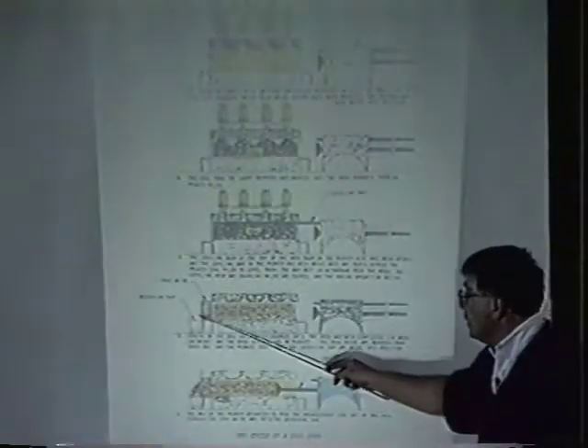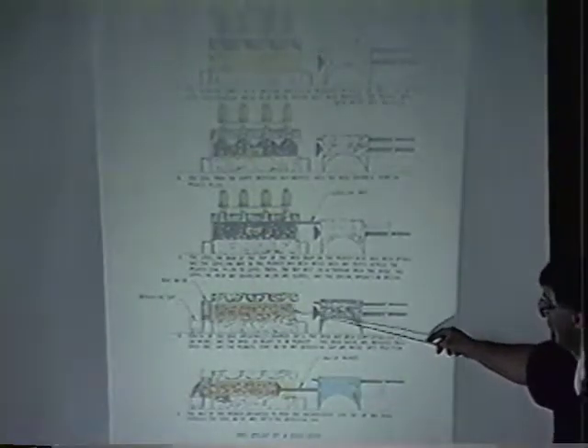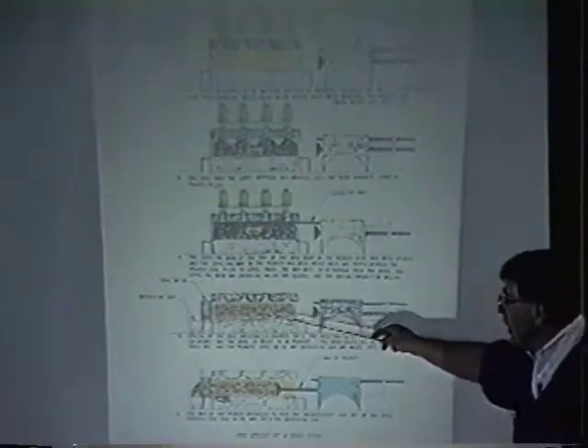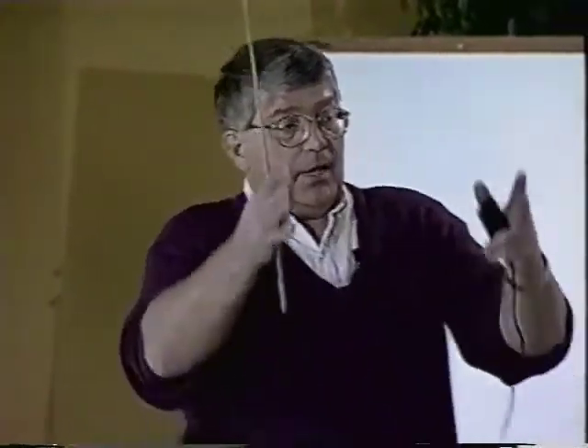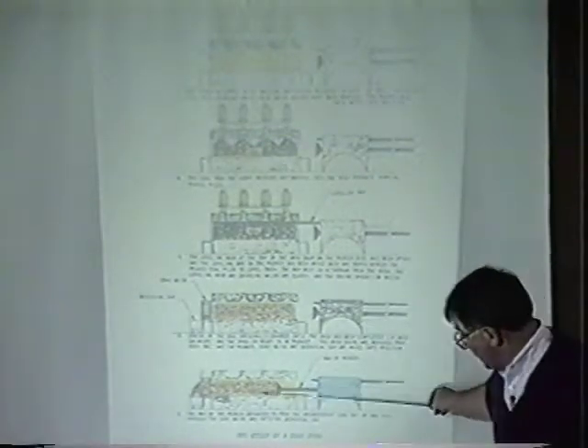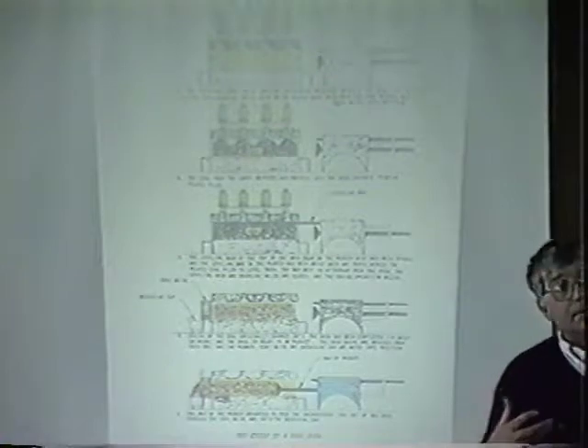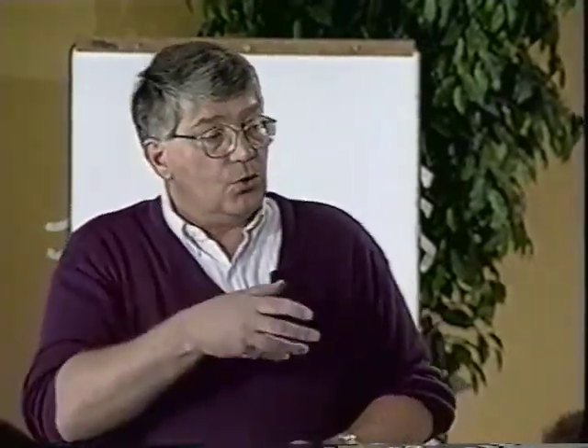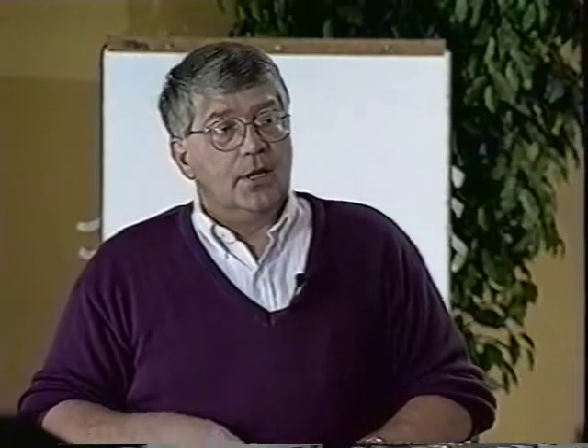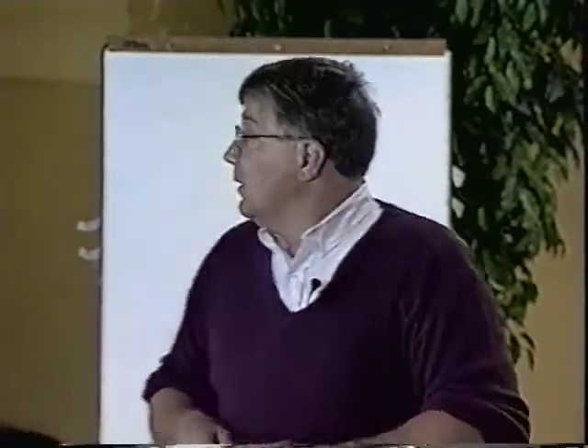Then after it sits in there, we have devices on the pusher machine to remove the oven door on both sides. And then we have a guide, we call a coke guide. And all it is is 2 slats, walls, that act as an extension of the oven. The coke is pushed by this ram on this pusher, as you can see, through the oven, and it stays as a mass. And it's collected into what we call a one-spot quench car. And like I said, it comes out about 2,000 degrees Fahrenheit. So we have to cool that so we can convey it to the blast furnace. So we take it down to what we call a quench station, and we quench it with anywhere from 8,000 to 10,000 gallons of water. Okay.